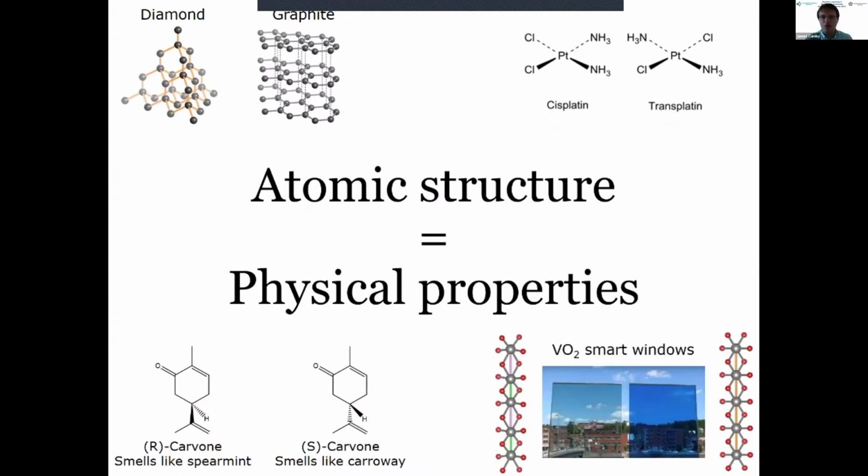But moving back towards the inorganic materials, a nice example is vanadium dioxide. This is an interesting material that's used in some smart windows, like you get on Dreamliner aircraft, when you used to be able to fly. These smart windows have VO2, which changes its state depending on temperature. Hopefully you can just about make out these pictures. At high temperature, all of your vanadiums in this rutile-like structure are the same distance away from one another. This is a metallic structure, so it absorbs quite a lot of light, which is why it appears quite dark in color.